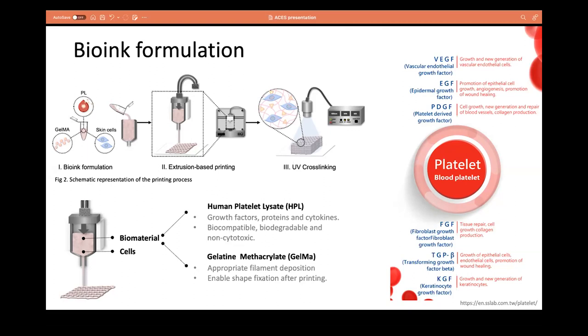For the printing system, we use an extrusion-based bioprinting approach. For the cell component, we started the characterization of the platform using fibroblasts, which are the major component of the dermal layer. But each and every compartment of the skin requires different cells, and they need to be distributed in a specific manner. For the bioprinting formulation, there are two main components: platelet lysate, which is responsible for the functional properties of the bioink, and GelMA, which is responsible for the rheological and mechanical properties of the bioink.